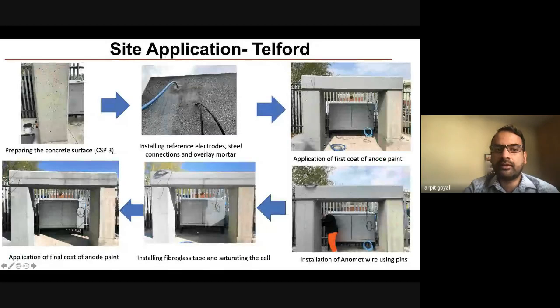This is another site in Telford. So this is the typical application method. We prepare the concrete surface, we install the reference electrodes for monitoring the potential values. We do the first coat of paint, we install the primary anode wires, we protect that anode wire using a fiber mat, and then finally do the second coat of paint. So it's a very simple application technique to protect against corrosion.